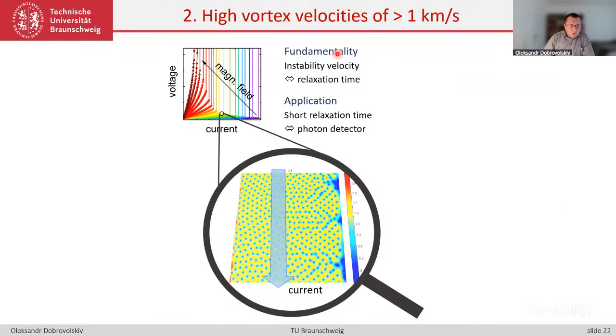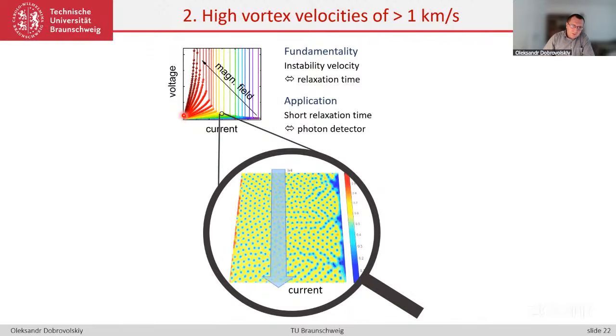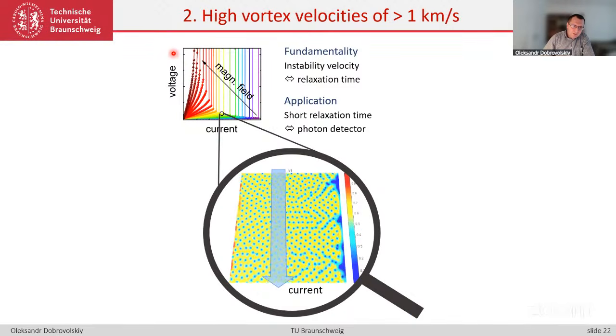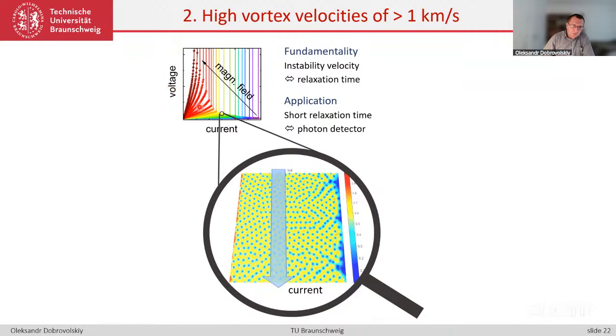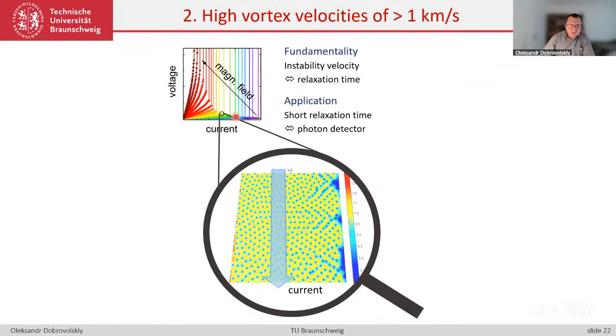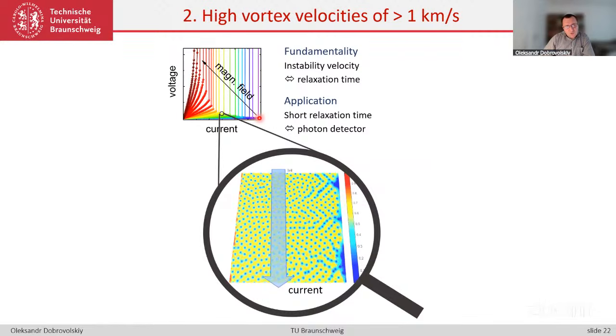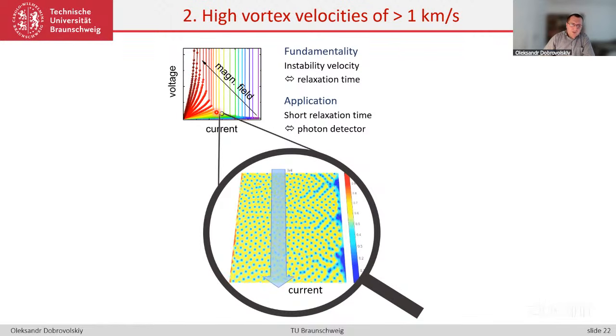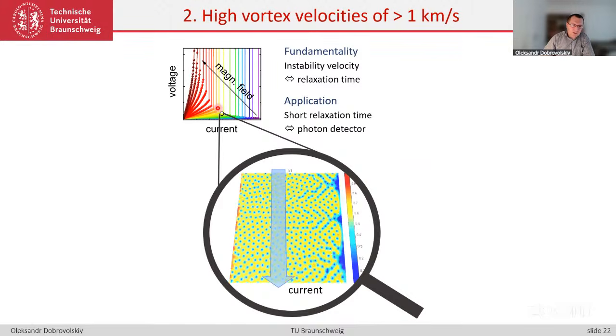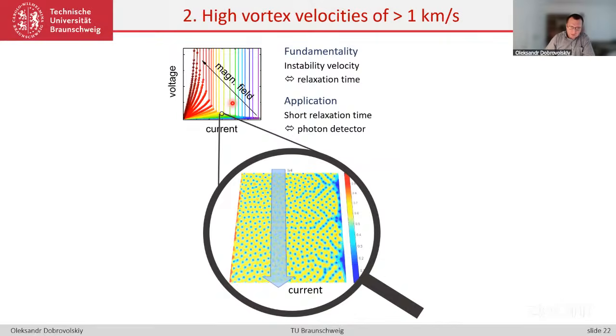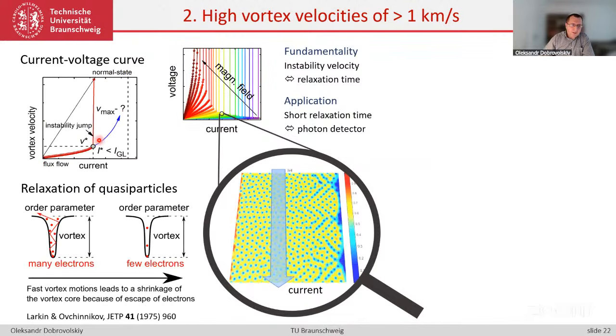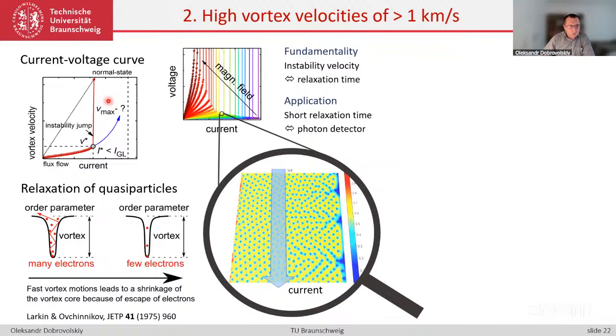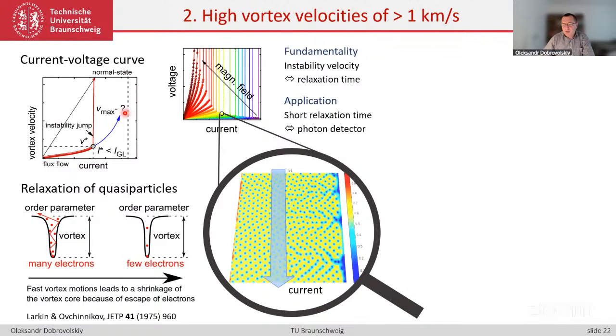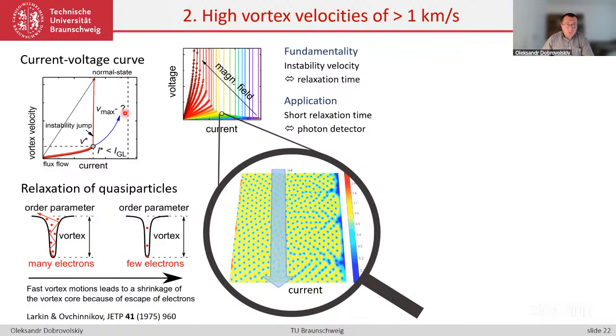Well, if one wants to accelerate vortices to higher velocities, typically what is measured experimentally is a representative series of current-voltage curves for a type 2 superconductor in the mixed state. What you see here is a series of abrupt jumps. So this superconducting transition is not continuous, it's not a regime of nonlinear superconductivity, but just a sudden jump. And the idea is how to tune the properties of the material in order to realize higher voltages, higher velocities, while providing the possibility for the vortex lattice to maintain its long-range order.